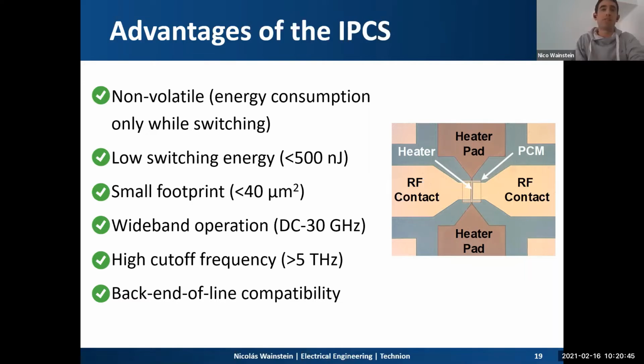To enumerate some of the advantages of this device, I want to highlight the high cutoff frequency, very close to the state-of-the-art, non-volatility, which means that there's no energy consumption while the switch is idle, just power consumption when switching the device. The relatively low switching energy compared to other devices, and a very small footprint. You can see here it's 40 micrometers squared. It might seem large, but believe me, when talking about transistors, as I mentioned before, to achieve low on resistance, we need hundreds of micrometers squared. So this is a small footprint. And also it's back end of the line compatible. This process can be adapted very easily to standard fabrication processes.